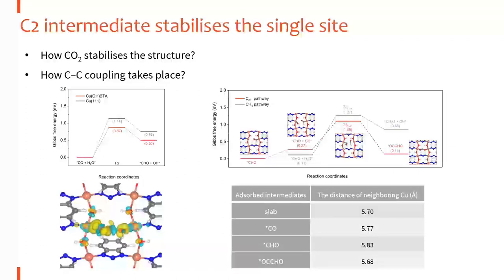We also analyzed the charge density during the reaction, and we found that once the molecule or the copper accepts one electron, the electron is favorably transferred further into the CO2 reduction intermediate.